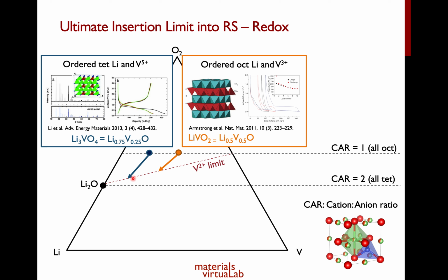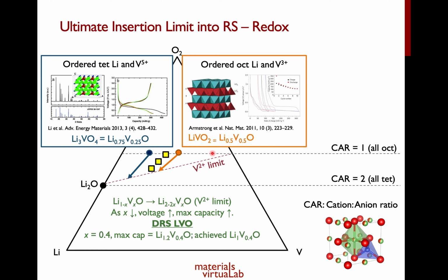Now, where the disordered rock salt operates is in between these two anode materials that people have investigated, which is these three yellow dots over here. Essentially, if I generalize the formulas for all our lithium vanadium anodes, you have a formula of Li1-xVxO. You can lithiate up to Li2-2xVxO, which is our vanadium 2+ limit. As your x decreases, when you move from LiVO2 to Li3VO4, your voltage goes up, because you are now increasing the oxidation state of your vanadium. However, your maximum capacity also goes up, because the length of this lithiation pathway is longer than this particular lithiation pathway. Now, in our disordered rock salt material, we are somewhere in between.